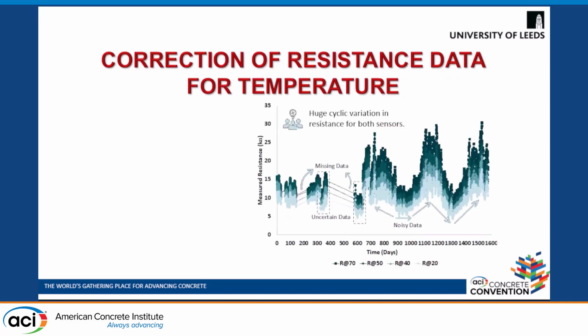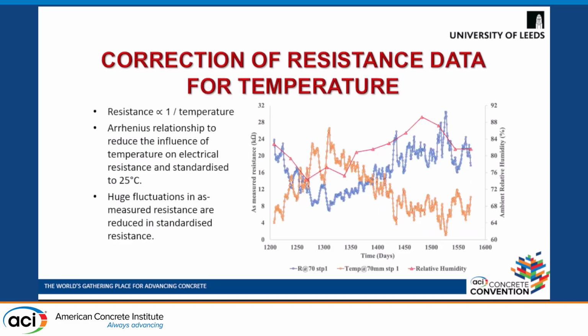As you can see in this raw data, there were huge cyclic variations in resistance for both the sensors, and this is majorly because the resistance is affected by the temperature measurements. With the increase in temperature, there was a decrease in the resistance. Therefore, this Arrhenius relationship is used to reduce the influence of temperature and standardize the measurements to 25 degrees Celsius. So these huge variations which were seen earlier,